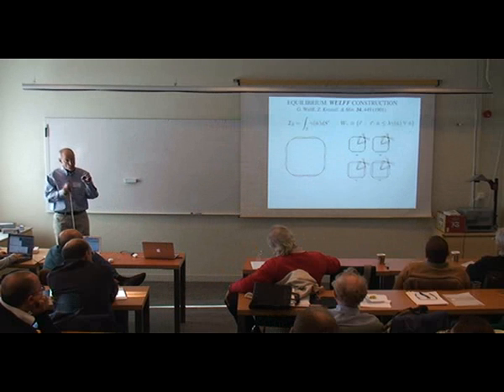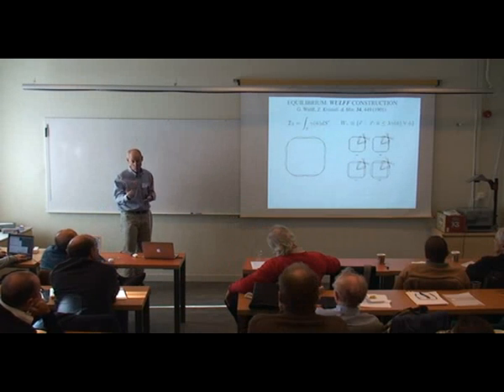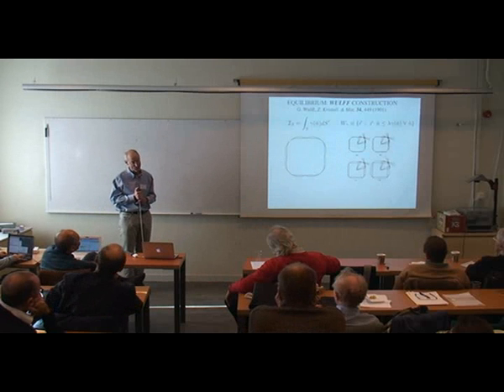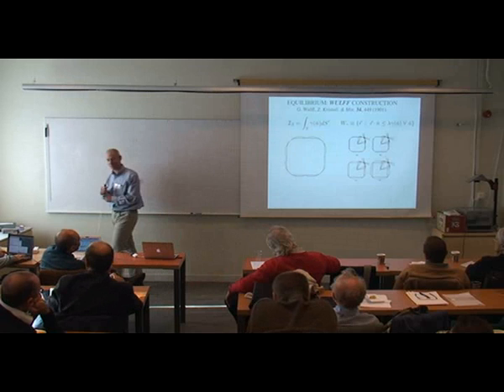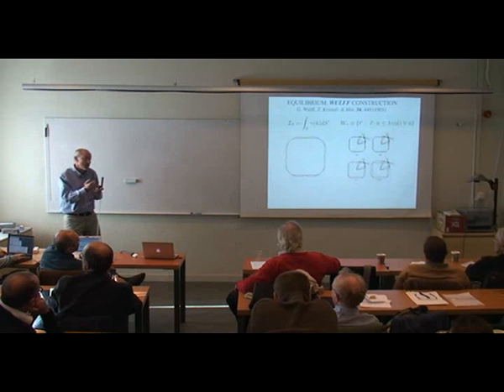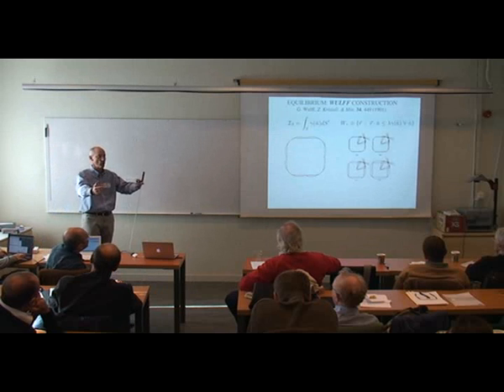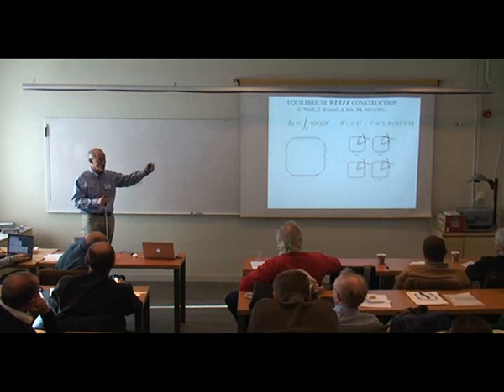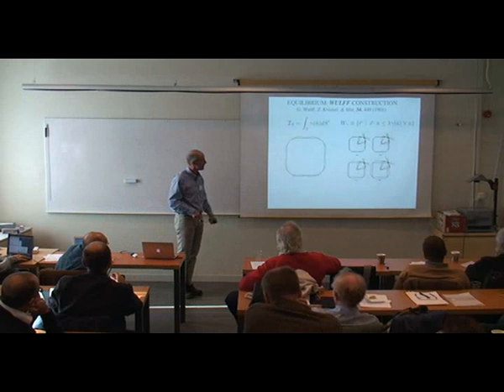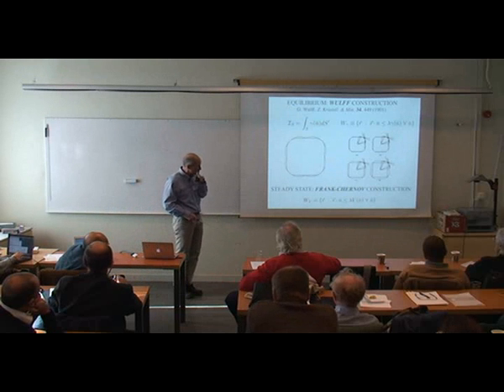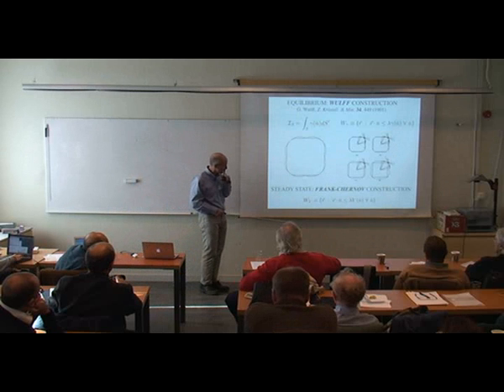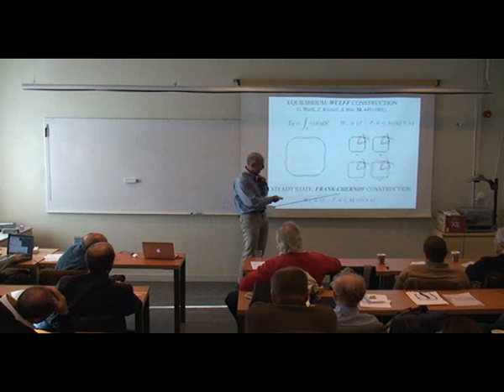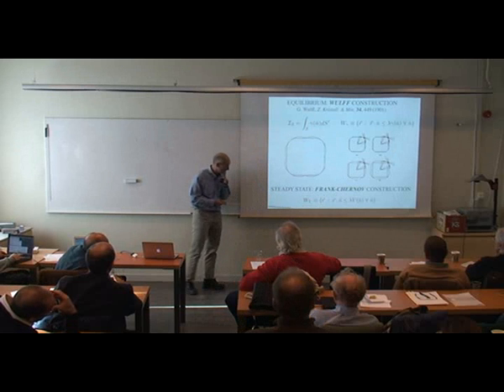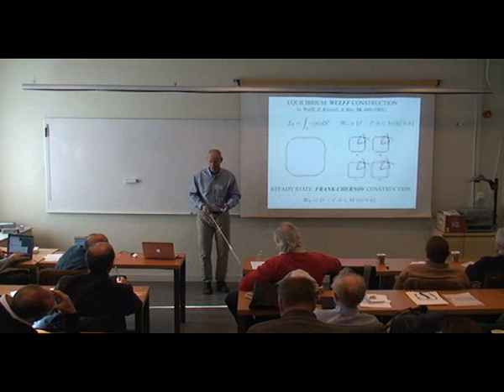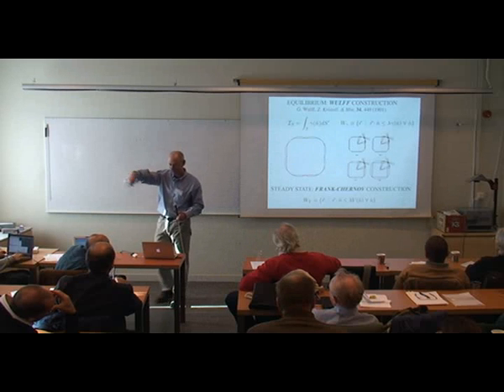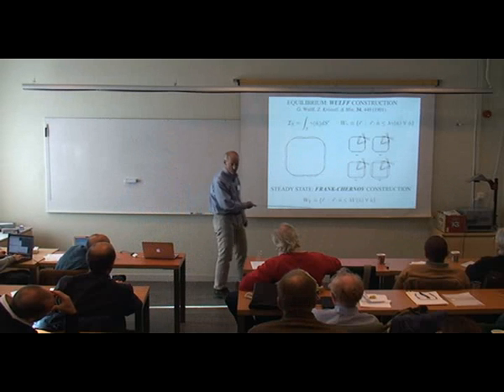Now it turns out that Wulff's study was actually motivated by wanting to understand crystal growth. So he has here a global thermodynamic equilibrium statement, which is that something minimizing its total surface energy is what gives me the growth form. That's what he was doing. We all now view this as the equilibrium description. Sometime later, and this makes contact with what I'll talk about in a minute, Charles Frank and Alex Chernov independently came up with the idea that if God or some close associate gives you the velocity of the normal everywhere, then the steady state shape is determined in exactly the same way.